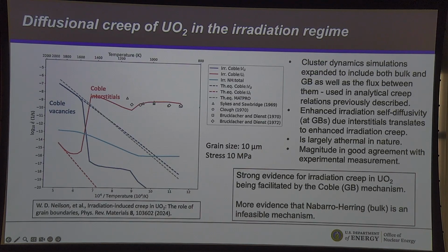By using the centipede cluster dynamics tool and coupling that to grain boundaries, we can capture all the physics here and make a prediction for what irradiation creep should look like. The agreement here is very, very good. That was achieved by allowing one parameter to change, but nevertheless, this really captures the relevant physics. And interestingly, while in the bulk, in thermal equilibrium, creep is all dominated by vacancies, the creation of defects on irradiation means that irradiation creep due to interstitials at grain boundaries is what explains this.